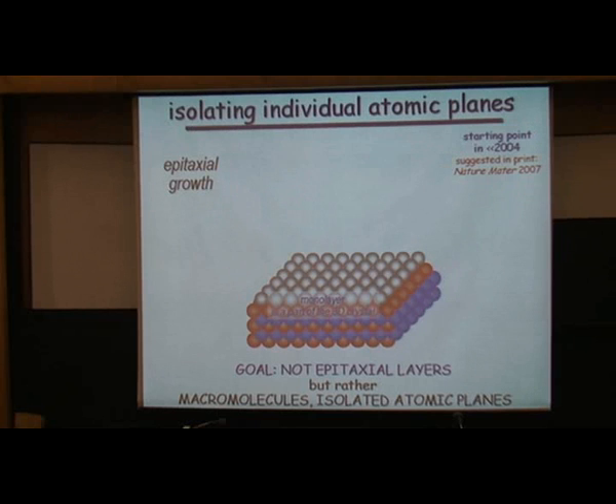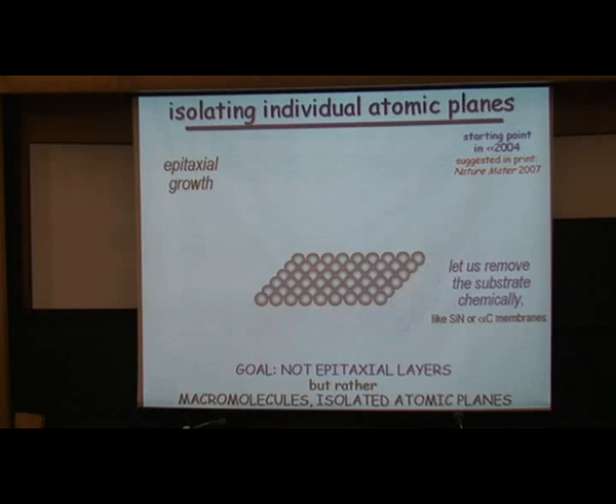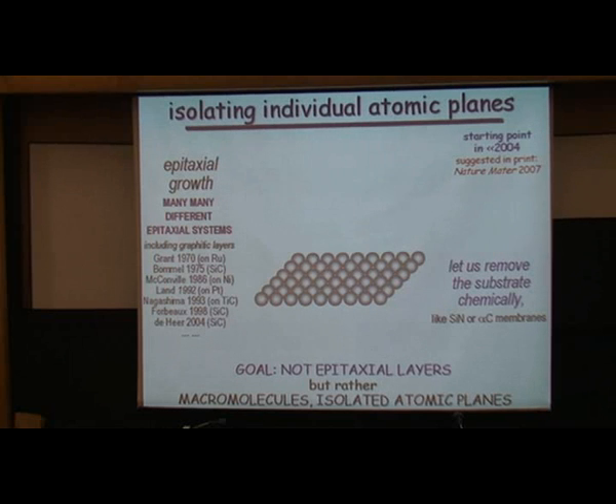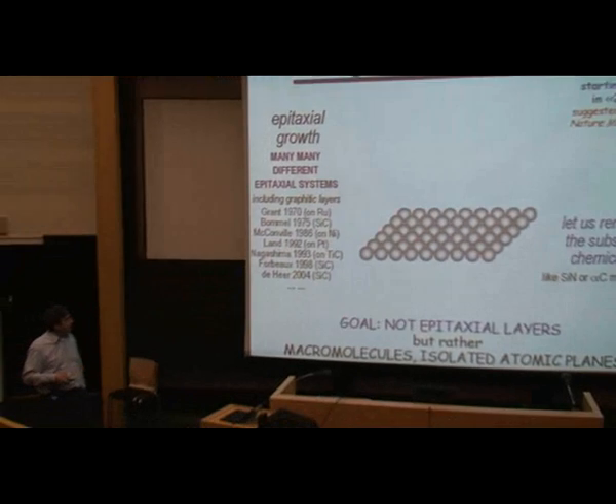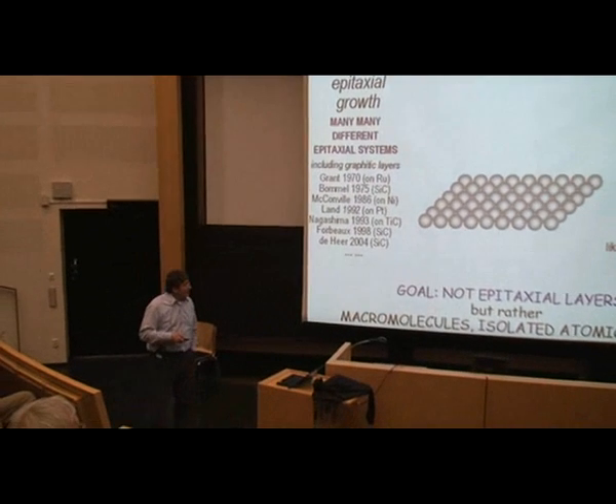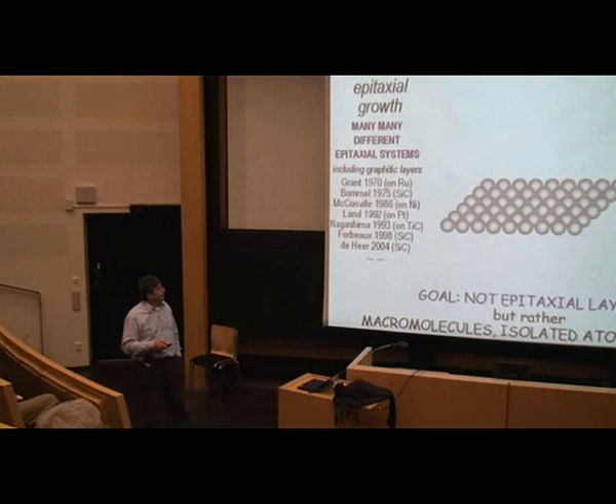So if we know this sort of system, the next step conceptually is very simple. You chemically etch the substrate. It has been done with materials about 100 angstrom thick, like silicon nitride and amorphous carbon. So we thought to do the same with different materials, and we shopped around. People do grow monolayers on various substances, including graphitic monolayers, but when you try to find something, it's really hard. This is nearly all the references before, and it's not really easy to get materials like that.